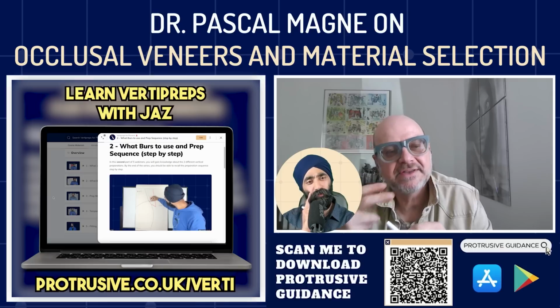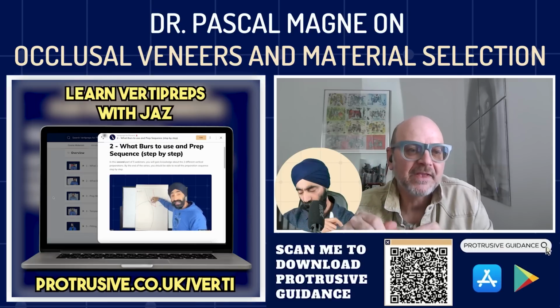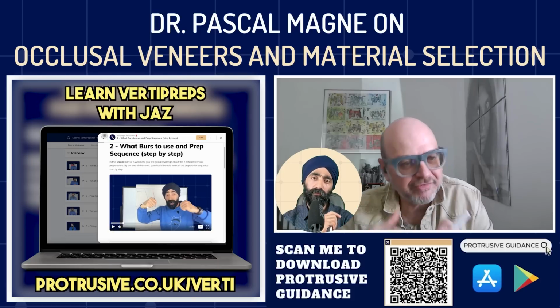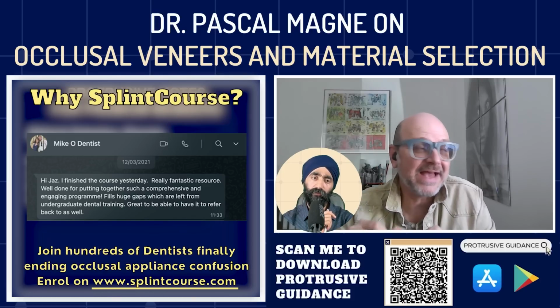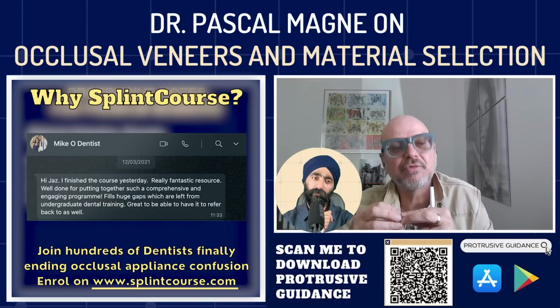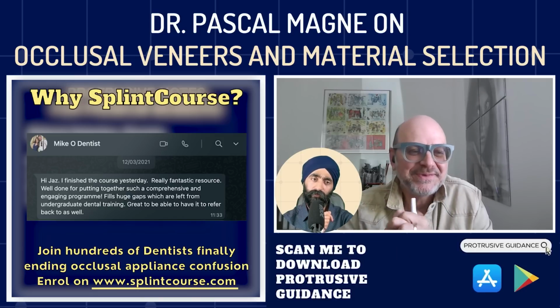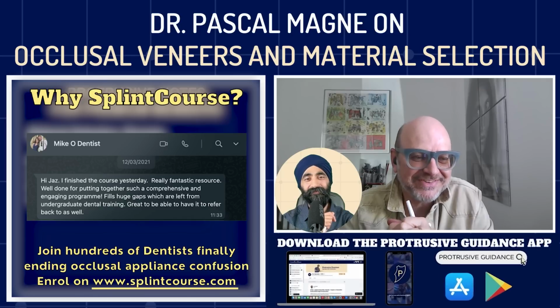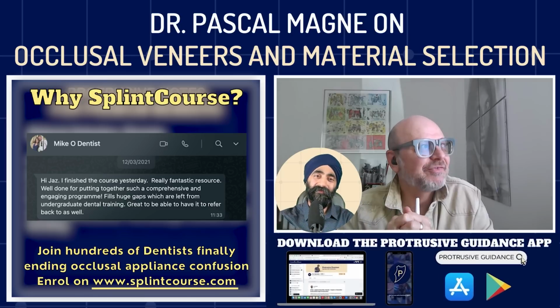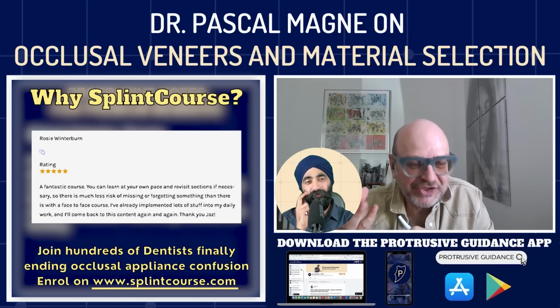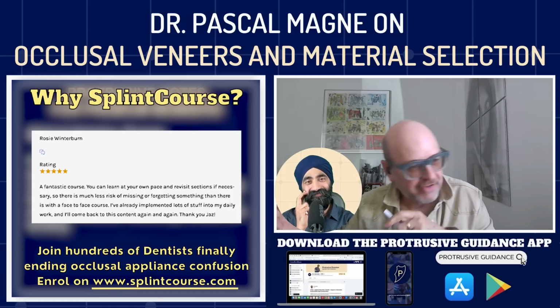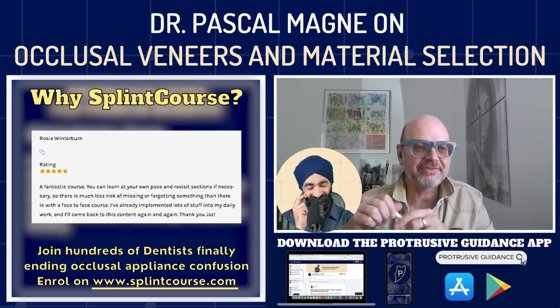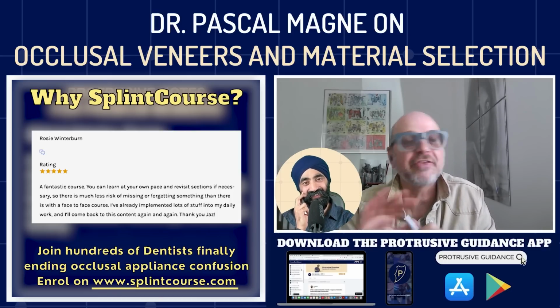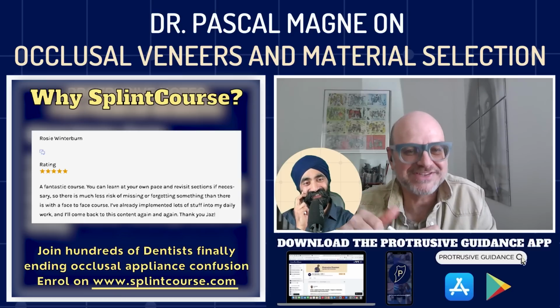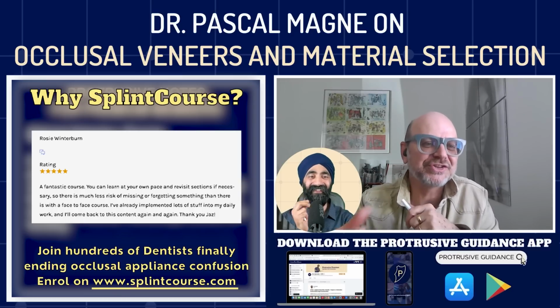The only monomer that will be useful is MDP. It's a phosphate monomer that's going to covalently bond to the zirconia. But again, that bond is susceptible to hydrolytic degradation. So you are making your life a little bit more complicated. When people ask me about zirconia veneers, what I tell them is if you are used to taking your restoration and dropping it on the floor, throwing it against the wall, stepping on it, and doing those kinds of things, then zirconia is perfect for you. You have more chances to have an intact restoration to bond.